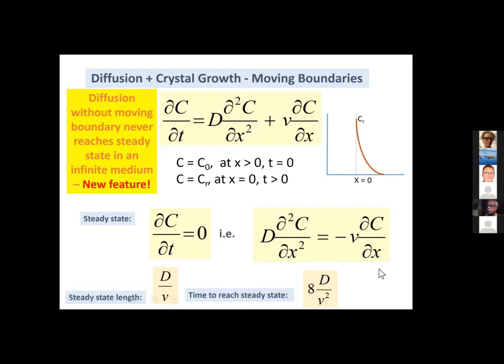So this is now the reverse. You have diffusion. You can measure the diffusion, but it is not a function of time anymore. So you have a profile. You can fit that, and you could get a number out of it, but that may be, again, a meaningless number. So that's a third thing that I'm telling you, where you have a profile, you can fit that, and you can get either a meaningless number or no number. So after talking about trying to do diffusion modeling to get timescales for many, many years, now I'm telling you all the cases where you need to watch out and not do diffusion modeling, because we're beginning to hit those limits in many cases now.